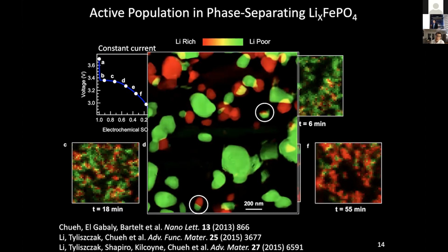If I show you a higher resolution image here, you can see that almost all the particles are either full of lithium, which is in red, or devoid of lithium in green, and only very few particles are actually actively undergoing intercalation, so it has a moving front of receiving lithium. So this is something that's very strange. We term this the active population effect, which means that only a very small fraction of the battery electrode is active for receiving lithium at any given time.